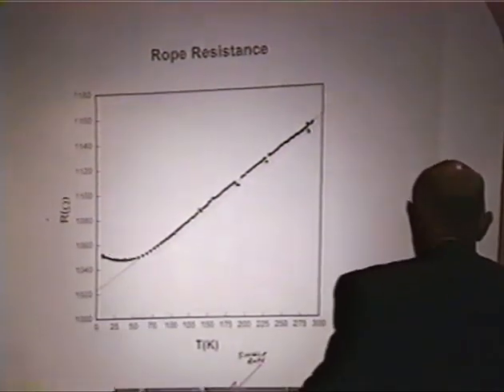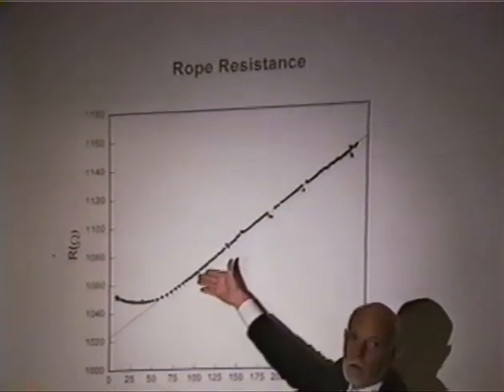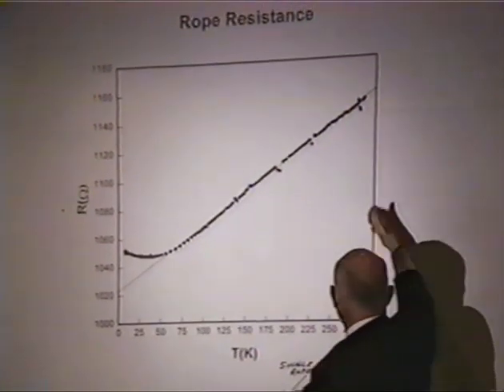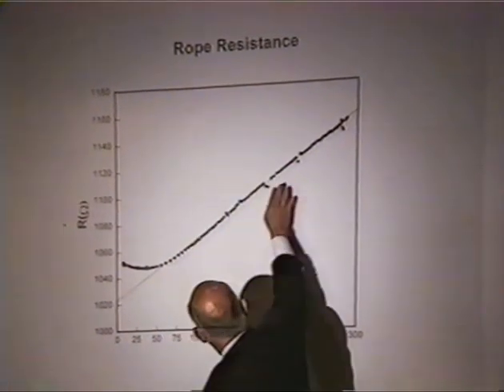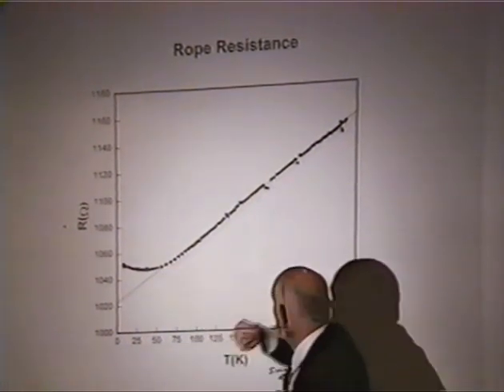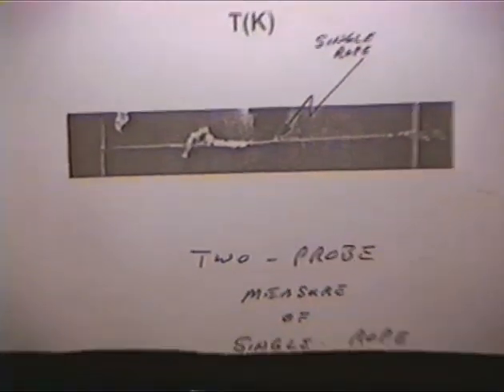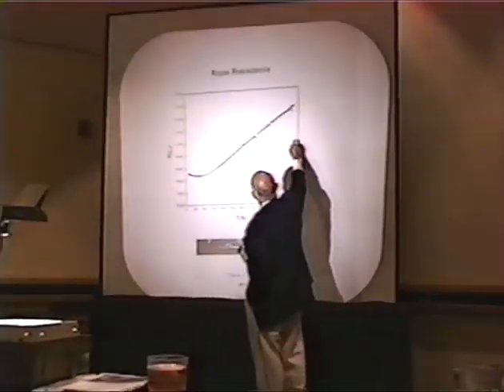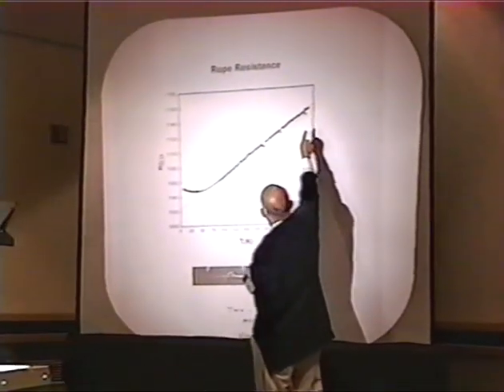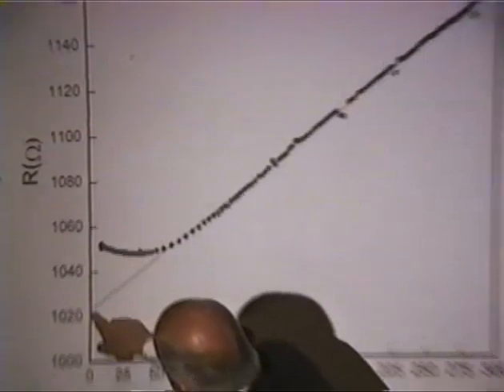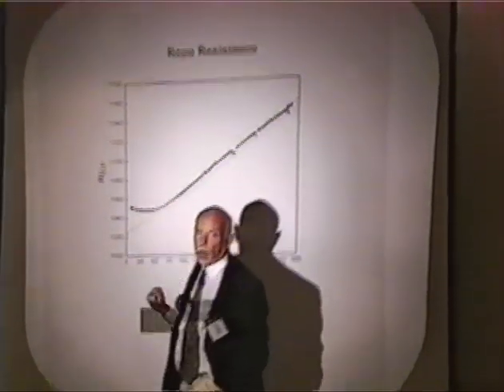It turns out that the temperature dependence of the resistivity of these metallic tubes is by and large linear over very large regions of temperature. This goes from room temperature down to absolute 0, and it's linear down here until about 50 degrees Kelvin. We know that these same materials continue being linear with the same, actually fairly slow slope, all the way up to 1200 degrees centigrade. This slope is quite small. Here at 300, we're at 1150 ohms, and down here at absolute 0 extrapolates to only a couple hundred ohms less resistance.